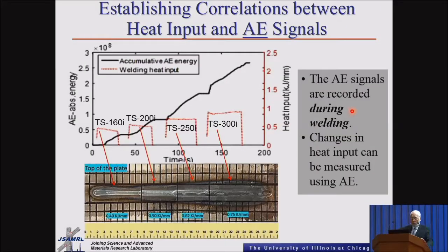All right. So now, having correlated the welding parameters with the quality of the weld metallographically, we decided to go and take a look at the NDE signals. First of all, we take a look at the acoustic emission signals. You can see that as you increase the heat input, you also have an increase in the absolute energy of the acoustic emission. So pretty much what we show in here is that the increase in heat input is being correlated with some of the changes that are being measured by using the acoustic emission.